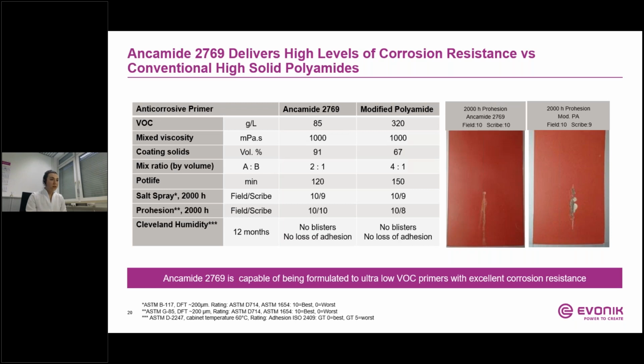To demonstrate the effectiveness of the new polyamide, the curing agent was formulated into an anti-corrosive primer. The formulation with a VOC of 85 grams per liter and 2 hours pot life is here prepared. The details of the formulation again you can find in our TDS, where it's listed what kind of pigments we use and which solvent, which level for this application. The primer can be spray applied with conventional spray equipment immediately after the mixing for 2769.